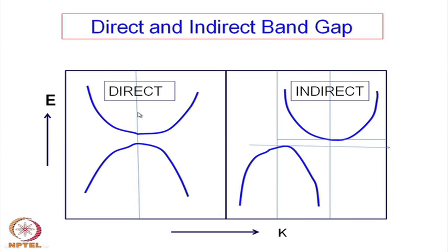Now, this is what we call a direct band gap. This is the direction of the motion. The electron is moving from a lower energy to a higher energy along this direction, and the bands across this direction, the lower band is like this, which means it is not flat at all, as we might have visualized. The surface of that band may be a completely curved surface, quite complex curved surfaces.